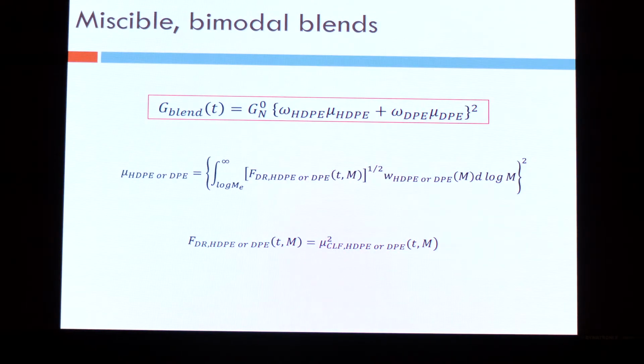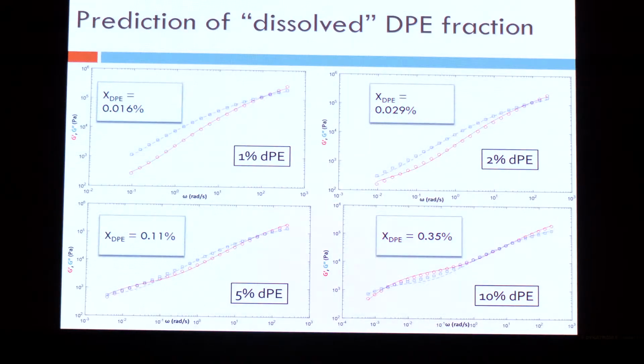Then we look at these blends, the blends of these two. We take all the theoretical equations and we actually now combine the theory and the experimental data. So now these are blends. In each of these figures, the square at the bottom right tells you how much disentangled polyethylene we have actually put in the mixing device. The square on the top left tells you how much of it actually dissolves. And this has come out of the theory.